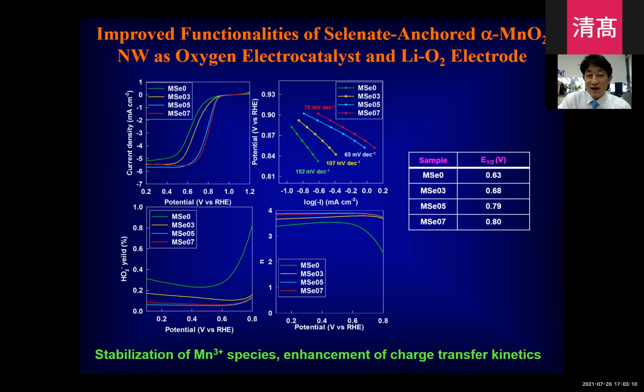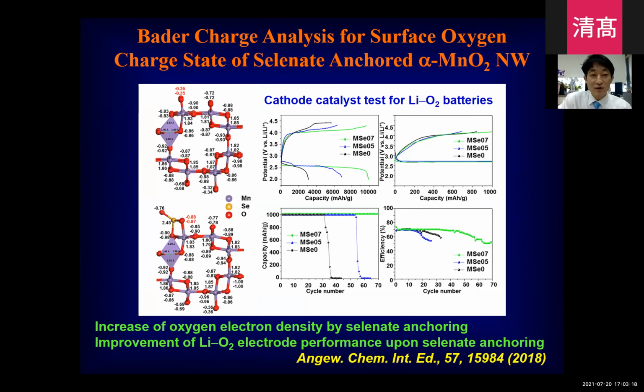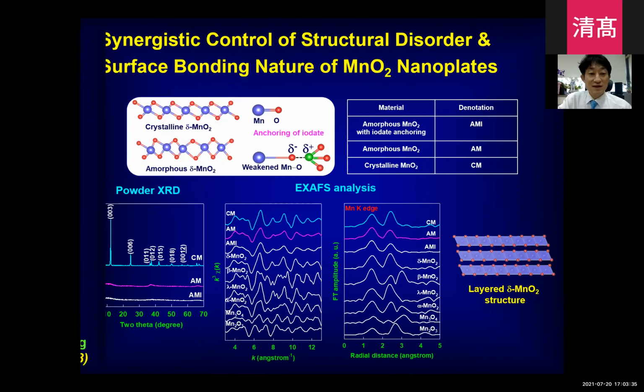Such selenate anchoring is very, very effective to improve the overall catalytic activity of the manganese oxide nanowire. So we applied those materials as a cathode for lithium oxygen battery, as you can see here. Such selenate anchoring is very, very effective to enhance the electrode performance of the manganese oxide nanowires. It's a similar result.